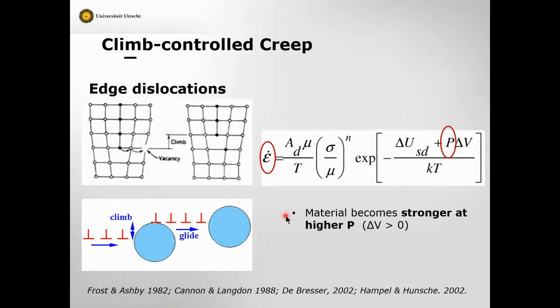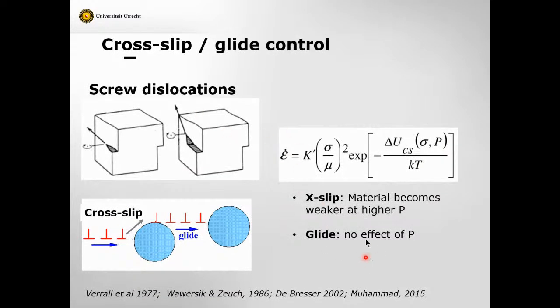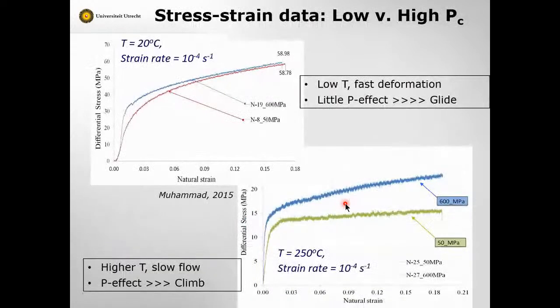So by doing experiments at different pressures, you could actually differentiate which are the actual processes controlling plastic flow and creep. And that is actually something that we did at our lab some years ago. Nawaz Muhammad did this in his PhD. Here are some results from constant strain rate experiments. These are done, for example, at room temperature. And this is typically the highest temperature we investigated, 250 degrees. You already see the effect at 200.